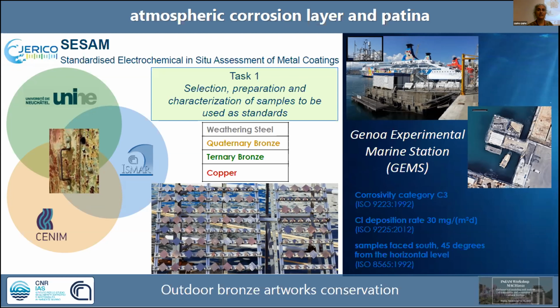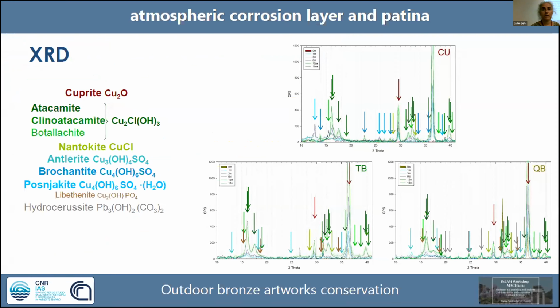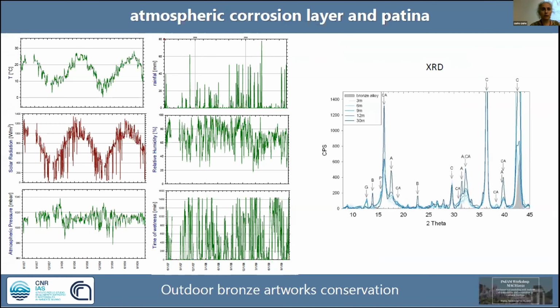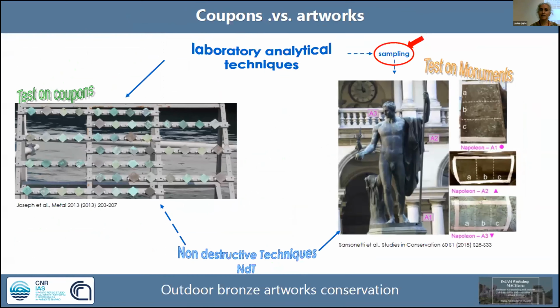And so here in this situation, we can follow the growth of the corrosion layer in conjunction with the climate parameters, the meteorological parameters, and with standard techniques. Doing this, we were able to find that the different compositions of bronzes, ternary bronze, quaternary bronze, copper, in the same environment were growing different kinds of patina. We tried some kind of correlation with the weathering parameters that are monitored during the evolution, but it's too much work. So I have plenty of data if you want to make some simulation.